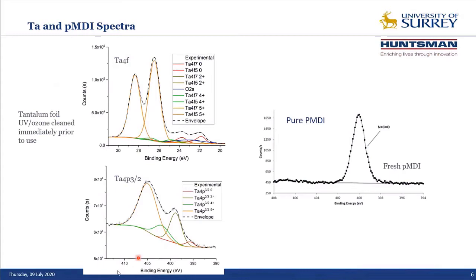If we now go and look at our tantalum 4p3/2 of the same sample, so this is just metallic tantalum after it's been cleaned in a UV ozone cleaner, hopefully removing most of the hydrocarbon contamination. This is the tantalum 4p3/2 peak. There's metallic tantalum and 3 oxidation states of the tantalum oxide, 2, 4 and 5. And we can see that the ratio is rather different to what we're seeing in the tantalum 4f. So that gave us a bit of confidence that peak fitting the tantalum 4p was the right thing to do.